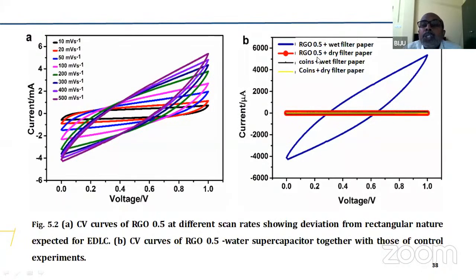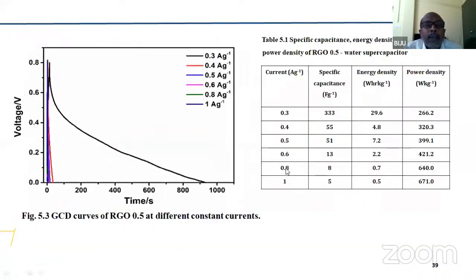The third one is RGO 0.5 and dry filter paper. So you have the active material, you have the separator, which is the filter paper, but there is no water present. Then also practically no energy is stored. But when the filter paper is wet, you have some area, which means energy is stored in the device. So this is the result that we obtained. Now, we repeated this experiment a number of times with different types of water: ordinary water, distilled water, double distilled water, deionized water, doubly deionized water, and of course pure HPLC water. And in all those cases, we got a similar result, that we can store energy at the RGO water interface.